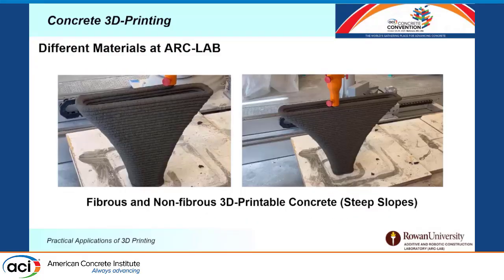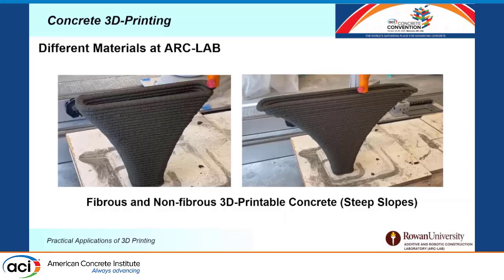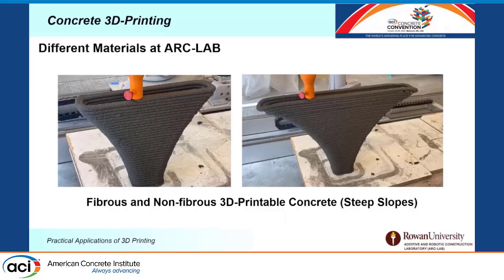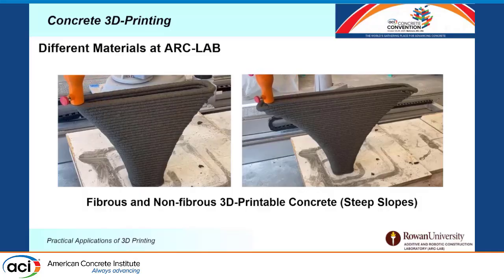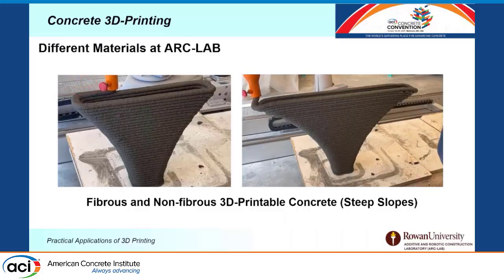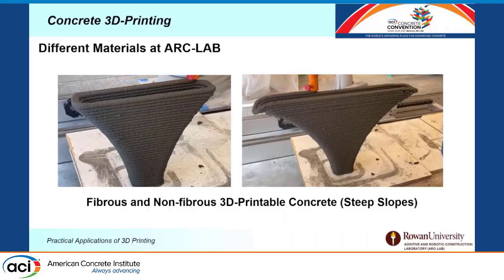This actually sparked an idea for us: without accelerant, how much slope can I retain? So we came up with a different design that is like a flare design. You can see on the left side a nice early version of it with fiber, on the right side without fiber. And we actually print and stress test the material to see where the weak point is and when it is going to fail. On the left side, you can see you start losing the shape, and material is extruding in the air, a little bit of a problem here around the left side, and almost partial collapse, that actually defined for us what could be the slope from vertical position.